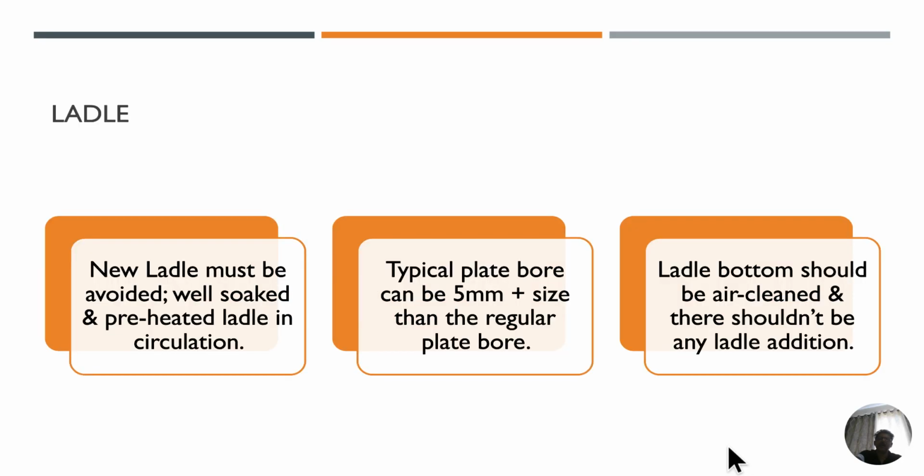A new ladle must be avoided; a well-soaked and preheated ladle in circulation is preferred. A typical plate bore can be 5 mm plus size than the regular plate bore. The ladle bottom should be air cleaned and there should not be any ladle addition.